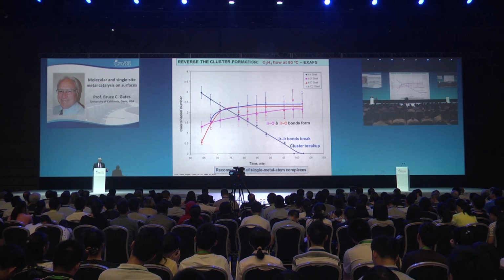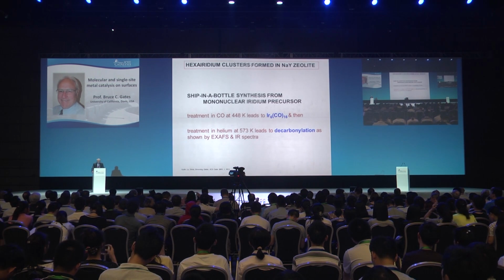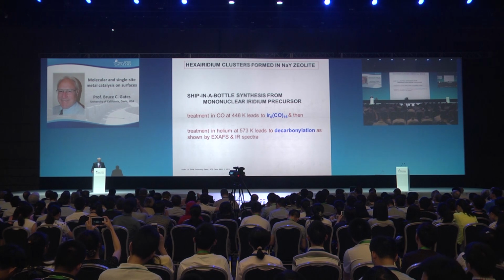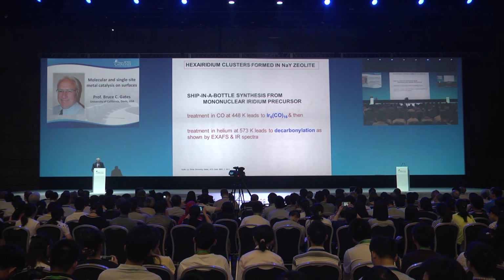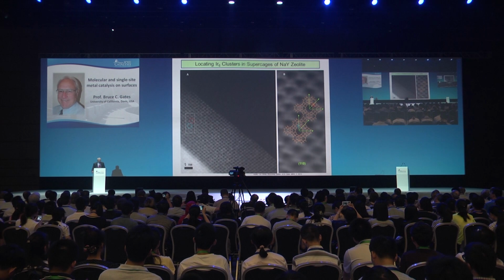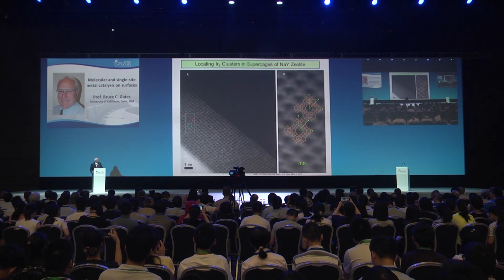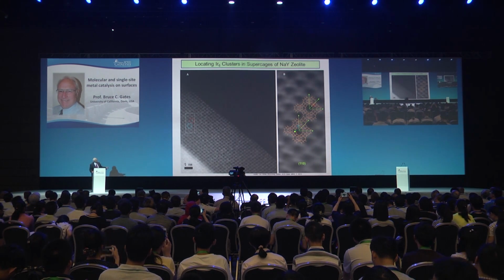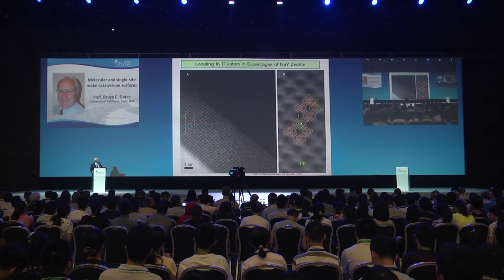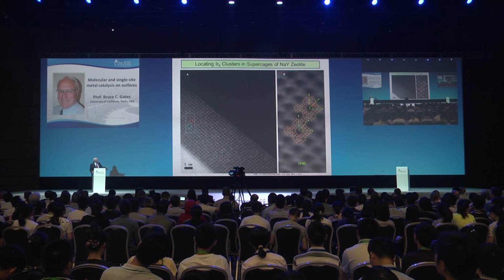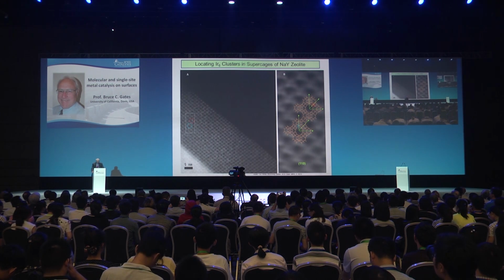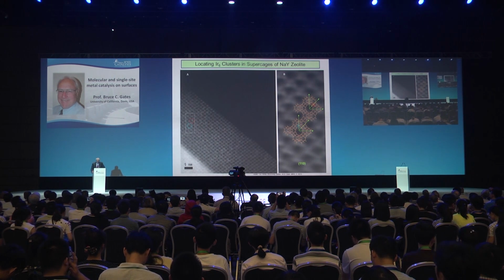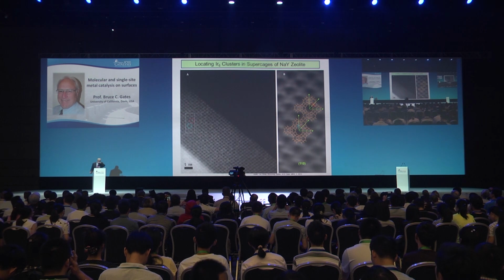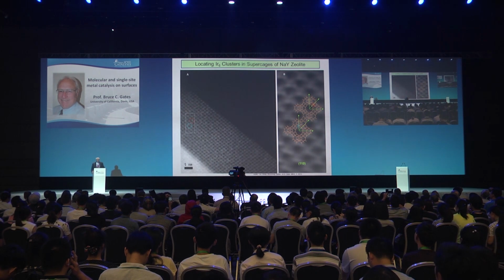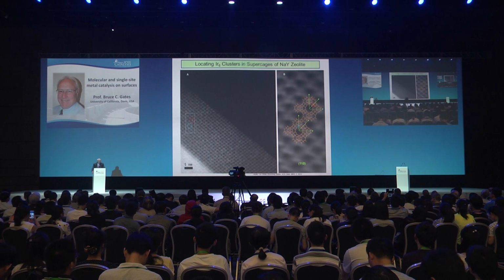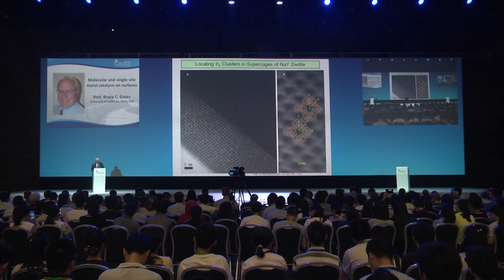So we're coming back to this. We can make other clusters in zeolites. Let's make a bigger one, a 6-atom cluster, and I'll leave out the details of the synthesis—you won't see the images very well, so I've put in a crutch and shown some of the metal atoms cartoonish to emphasize where they are, but we form iridium-6 clusters in the zeolite pore. So this is a ship-in-a-bottle synthesis, but it's also precise.